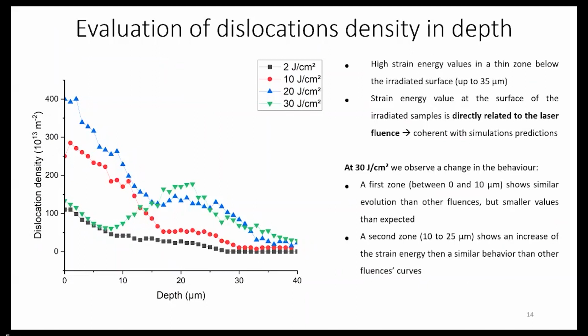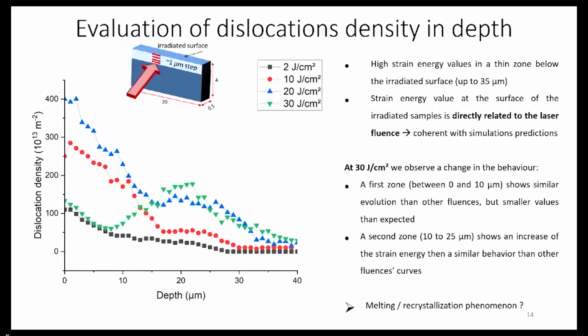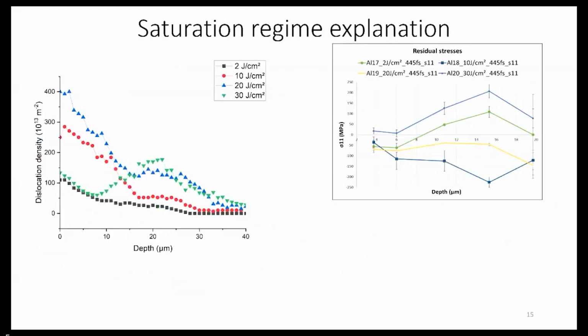So in order to explain this difference, I have done some other characterization from those measurements. The first one is the residual stresses measurement. What you can notice here is that for the first three values, which are those first three curves, the values are negative, meaning it's a compressive residual stress. And for the other one, the one with the different behavior, we can see that these residual stresses are positive.